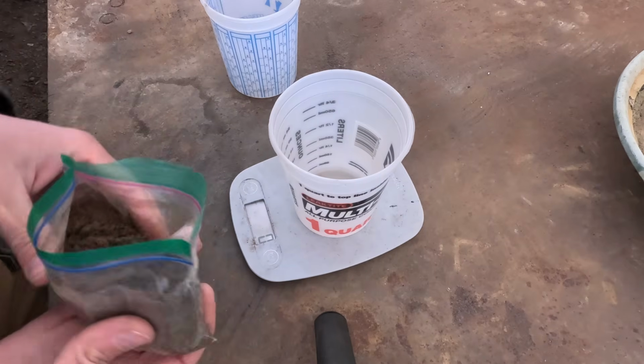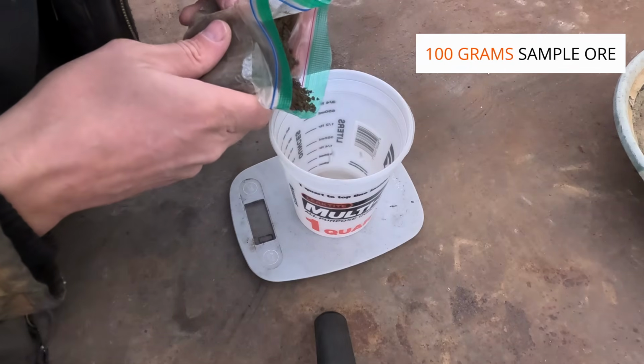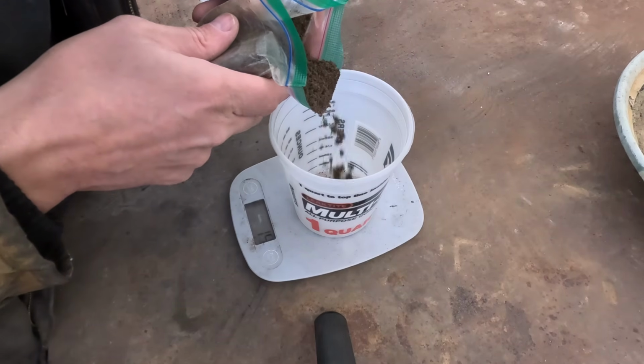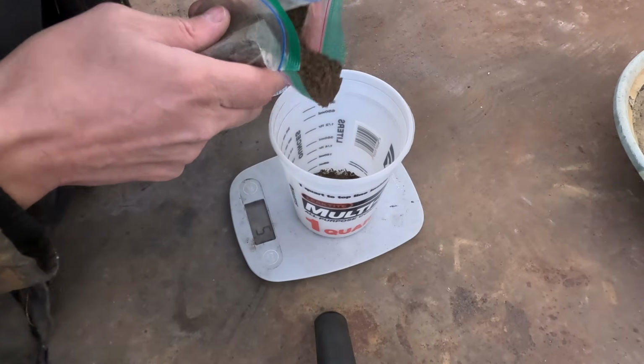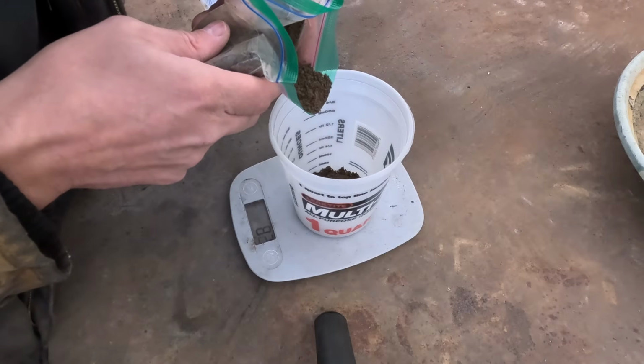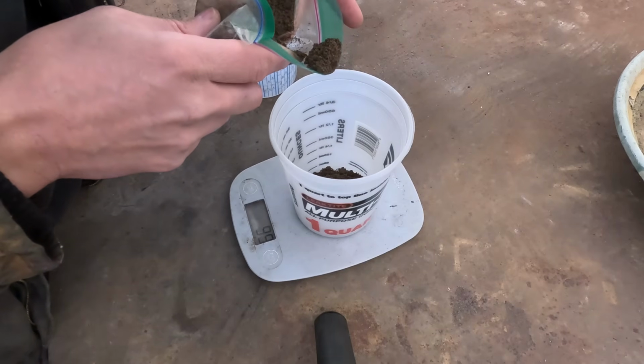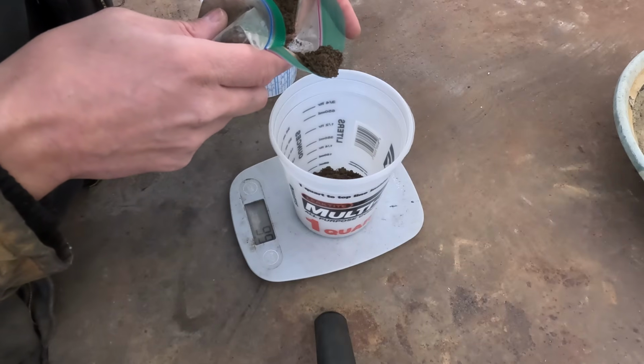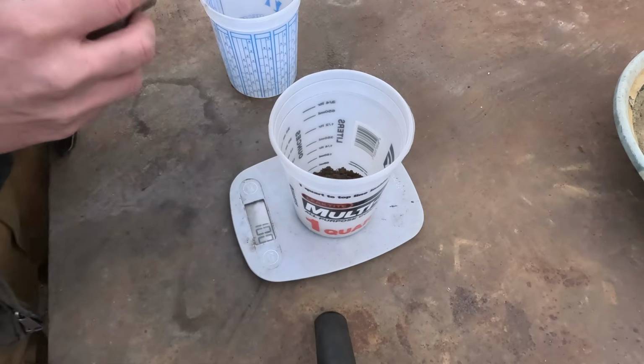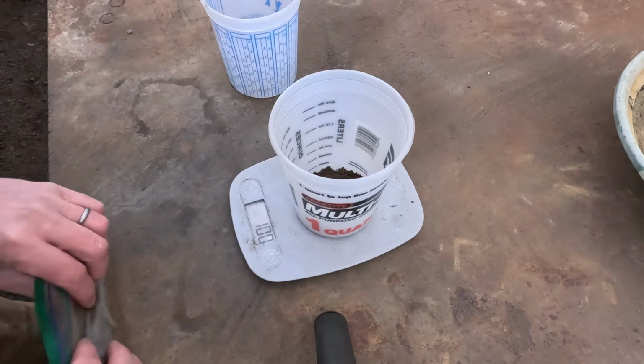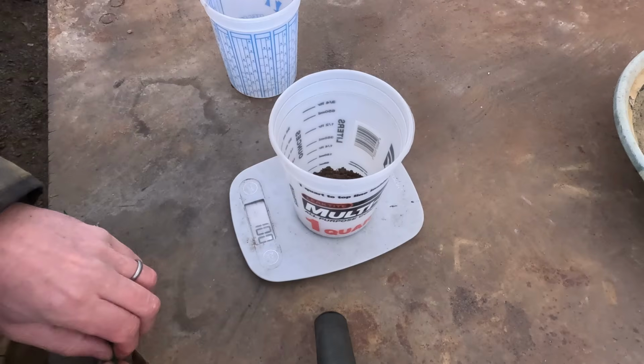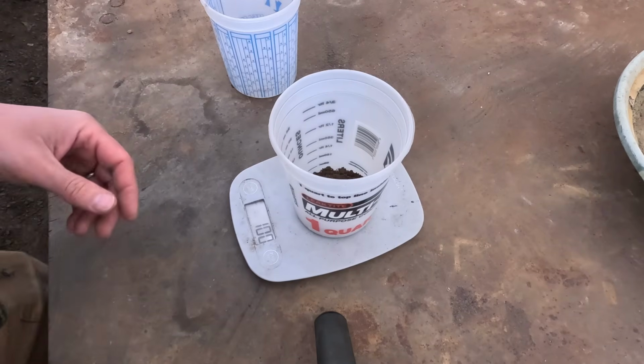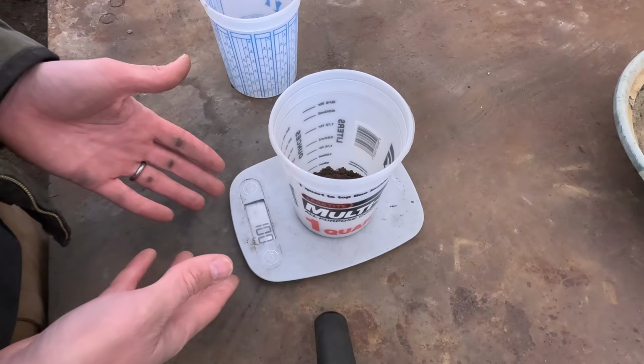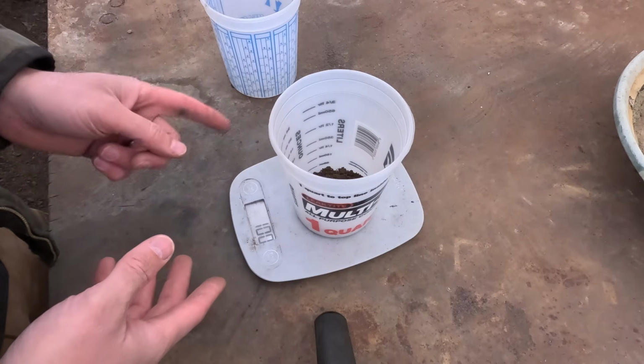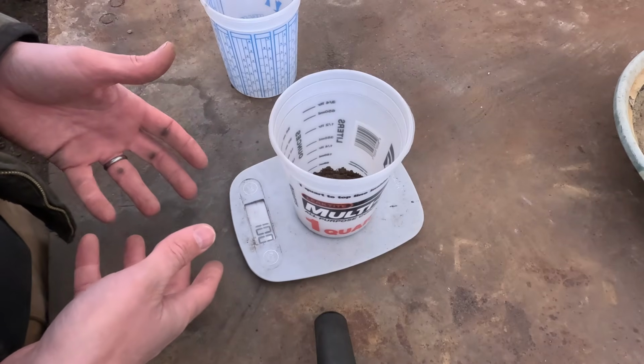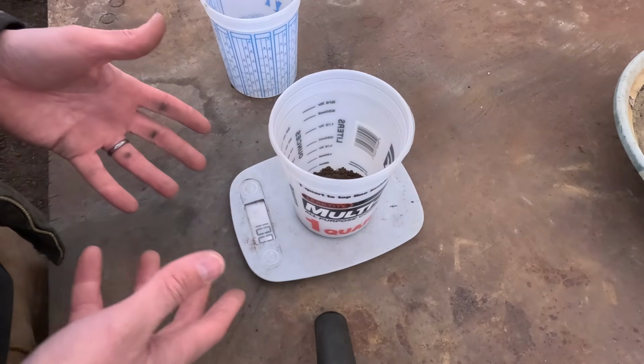The first thing we're going to do is weigh out 100 grams of sample. Now there's a couple different ways to do this. I like to use 100 grams because it makes the math really easy, and because I'm doing only one smelt or assay at a time, I can use a little bit more. Typically when you do fire assays commercially, you use what's called an assay ton, and that's based on the US system in ounces per ton, but I'm trying to move towards the metric system here, so I'm going to use 100 grams. So what that will do for us is when we get our final result in our precious metal bead, we can just move that decimal place over and we'll really easily be able to see the grams per ton, per metric ton in the sample.